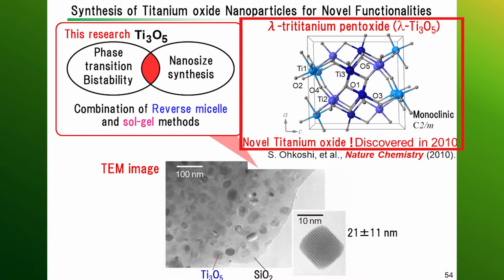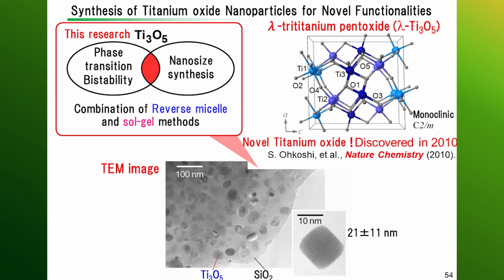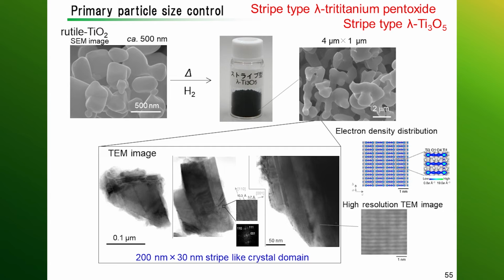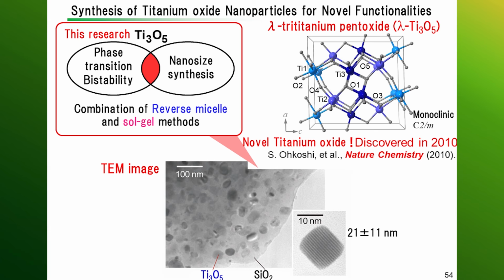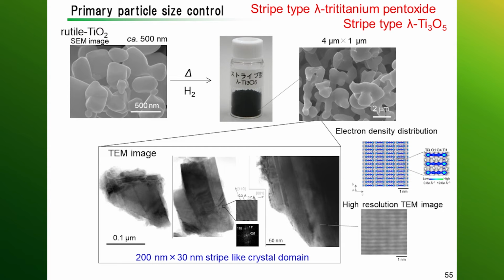And the glass can be chemically etched to remove nanoparticles, but we wanted to make large amounts of nanoparticles, so we thought of targeting small particles and avoiding growth into crystals. That's what we thought of, and the result was we were able to get large amounts. At first glance, it looks like a huge coral reef. This is 2 microns. The previous page was 20 nanometers. So if you look at the one on this side, it's 2 micrometers, which is 2,000 nanometers, which is 100 times the size.